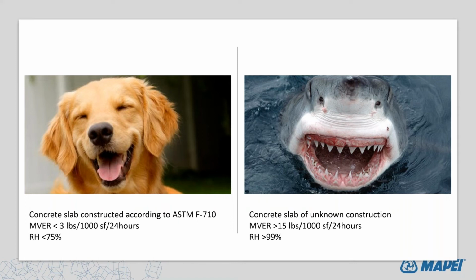And when we're talking about high moisture conditions, a concrete slab that is your best friend is not high moisture. It's less than 3 pounds of moisture vapor emission rate per the ASTM F1869 test, or an RH level of less than 75% using the ASTM F2170. Again, these are almost, I should use a unicorn for this kind of picture. They're very hard to find.